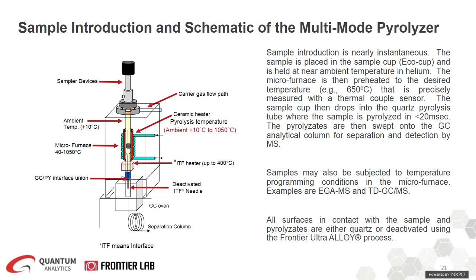The pyrolyzates are then flushed onto your GC column for detection by the MS. So using this technique, you are performing a continuous mode pyrolysis, where your sample is held at an ambient temperature while the furnace is preheated. So your sample does not get exposed to any heat prior to the analysis. As a result, there won't be any degradation or evaporation of the lighter components prior to your analysis.